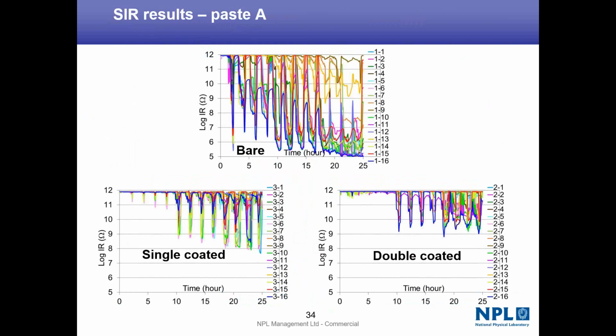And this is just an example of a bare board, a single coated board, where we've actually taken the board and then coated it with a conformal coating and a double coat. So this wasn't necessarily to look at the performance of the coating, it was to see what we would see when we were running through the test. And you can see here a bare board with this quite severe test. You can see a quick drop in the insulation resistance.